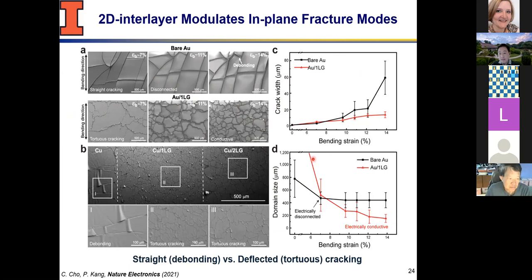You can see that for the bare gold alone, you start to see continuous increase in width, whereas that of one layer inserted gold starts to have more of a saturation behavior. And also the domain size keeps decreasing. So they're breaking into smaller pieces as you keep applying strain, whereas this basically gets saturated. So it gets saturated, so there's no further energy dissipation mechanism. You start to enlarge the gap between these domains.